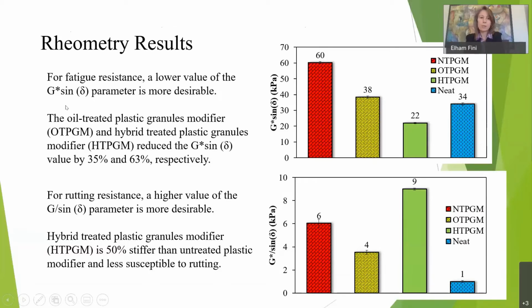For that, we have this measure, which is a standard used in the Superpave specification, which is G star multiplied by sine delta, a rheometry characteristic. We basically measure that and then compare it for different samples. Again, you can see the red, the yellow is the oil-treated one, and the neat here is the asphalt that doesn't have any plastic.